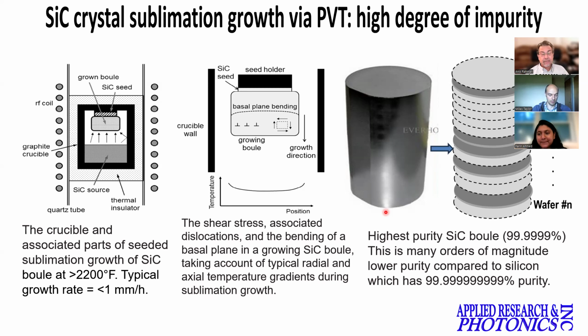But in silicon carbide, these wafers are much thinner. These are only 350 micron thick, even though that's thinner, because silicon carbide is way harder than silicon. So you can make much thinner wafers. Except the boule growth here is limited to only 50 or so millimeters. You cannot grow a 1 meter or 2 meter long boule in silicon carbide. Why? I mean, that's an issue. Of course, you can easily see that's an issue.